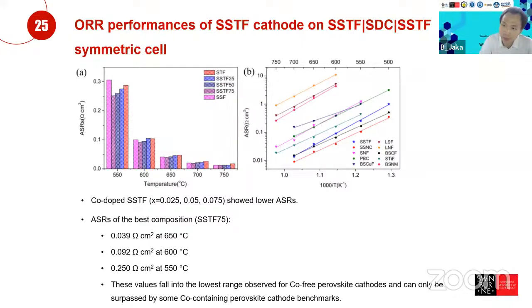Okay, and then when we compare this with the other materials as well, as we can see in here, our material SSTF is located not too bad. It's located at the lower end of the ASR, which means that the only other cathode compositions that can beat this particular composition are only BSCF and SSNC.